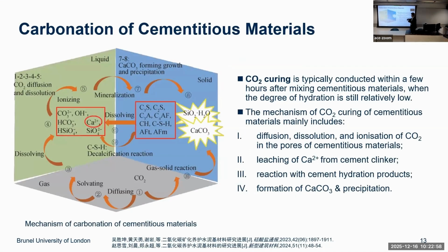So if you talk about curing, carbon curing happens in the first few hours after cement is mixed with water, and before final setting. This process involves the diffusion, dissolution, and ionization of carbon dioxide into the pore solution of the cement paste, because carbon dioxide immediately dissolves in the solution. There is also calcium ion leaching from the cement clinker. Then they can react together to generate calcium carbonate.